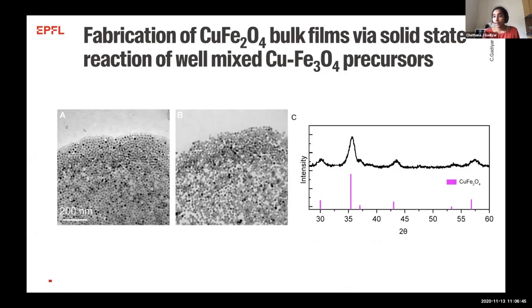So the next step that we did was to make bulk films of copper iron oxide. What we understood from this study is that we wanted a very well mixed copper iron oxide precursor to be deposited. We were able to achieve this by controlled drop casting of very dilute solutions of copper and iron oxide, which ensured that there is always a well mixed copper iron oxide precursor on a thin film. When we annealed such a sample to a higher temperature, like 750 degrees Celsius, we were able to form phase pure copper iron oxide films. And this was also confirmed using X-ray diffraction from these thin films.